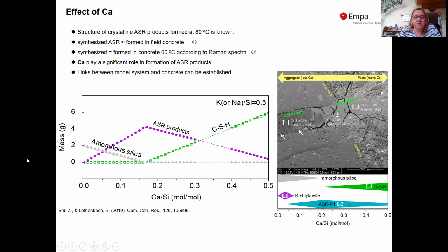We also can now compare these calculations with what we've seen experimentally. Again, we have here plotted the calcium to silica ratio in the experiments. We have here plotted the mass of ASR product which might form. And we can see we have a sequence from ASR product to CSH, which corresponds to what we've seen in the experiment, in aggregate. We have here a crystalline ASR product, we might form an amorphous one, and eventually we have CSH.